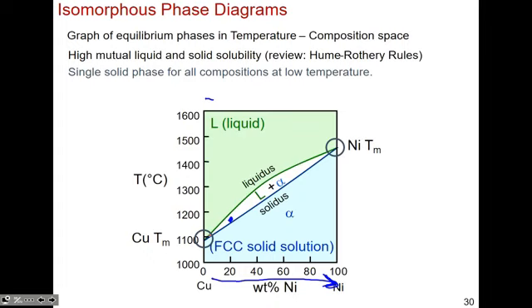So at that temperature and that composition, you're telling me, according to this phase diagram, that there's some precipitates. There's already some solidified copper nickel, at 20 weight % nickel. And not all of it has solidified yet. That's all you've told me. But the fact that I can see this phase diagram, I can say, it's an isomorphous binary phase diagram, so that means they're going to form this solid solution. It's going to mix very well. Great. I just have to wait for you to drop the temperature, and then we can have the solidified form.